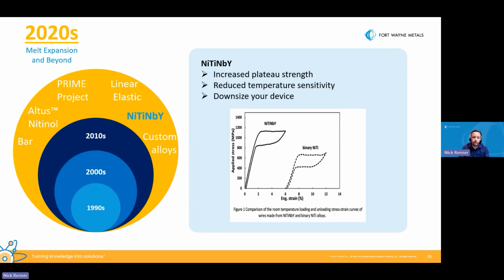Our nitinol niobium yttrium is a combination of processing and alloying, creating an increased plateau strength, about 50 to 100% when compared to a standard binary. One of the byproducts of the addition of the niobium and the yttrium is reduced temperature sensitivity. We've seen this material behave superelastic in cryogenic conditions or temperatures. So if you need to downsize your device while maintaining strength, switching to this alloy may be an option. Or if you have an application with a harsh, uncontrollable environment, this could be an option as well to maintain superelastic properties.